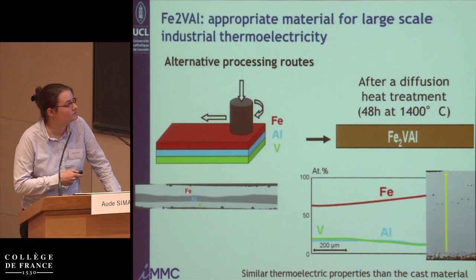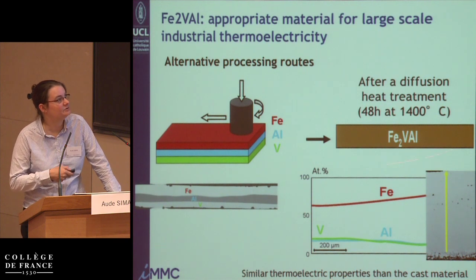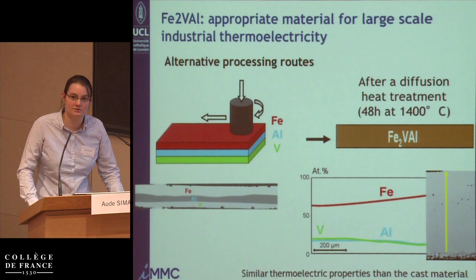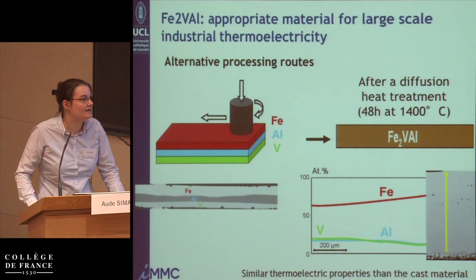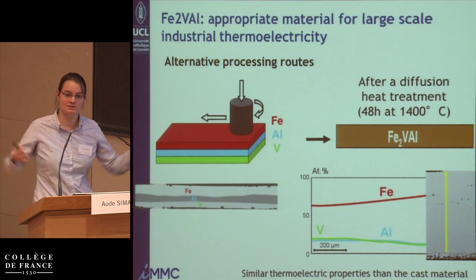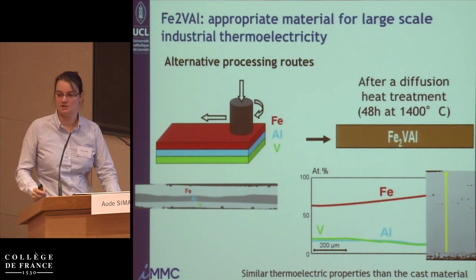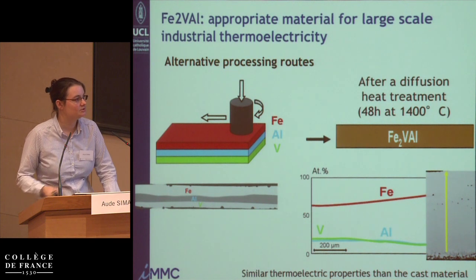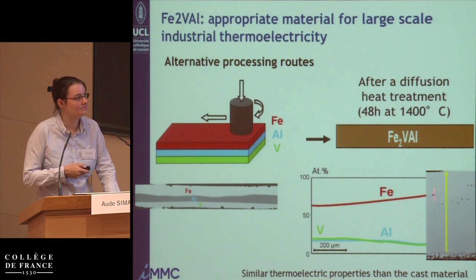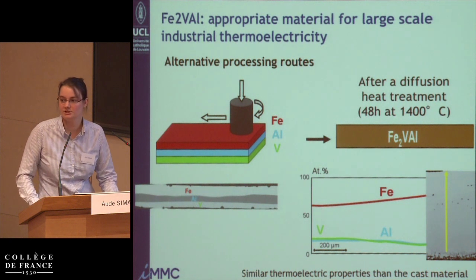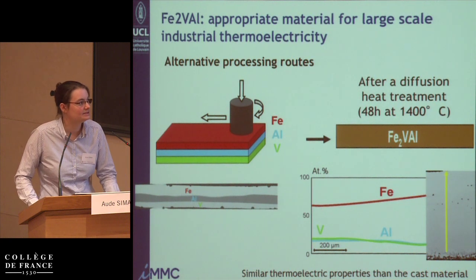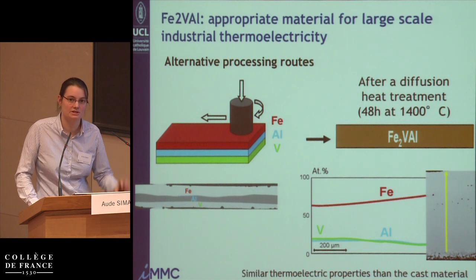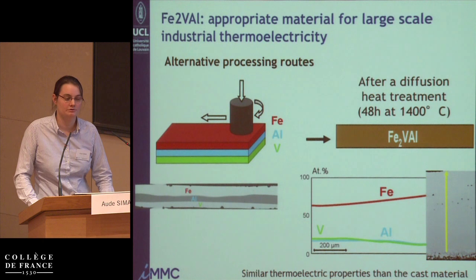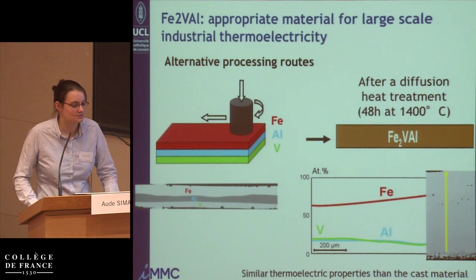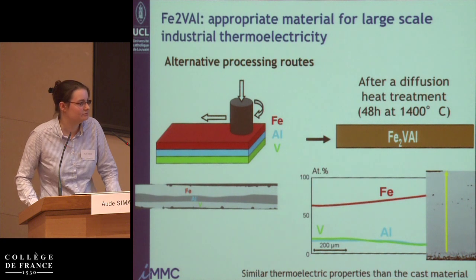And so we welded iron, aluminum, and vanadium, melting the aluminum layer. And after a heat treatment, 48 hours at 1,400 degrees C, well, you can get Fe2VAl material, a bulk material that's already at a nice plate shape, and so that's quite interesting. But you see that there still is some heterogeneity of composition along the thickness, and that can be exploited also for changing the thermoelectric properties from one position to the other. So it might be interesting to also try to exploit this.